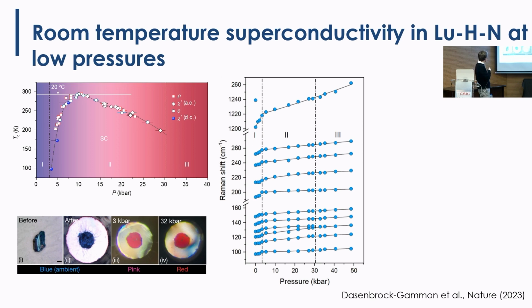They were saying that the sample had a very weird color change. So it was going from blue to red, okay? And then they also measured the Raman, and there were some phonons around 250 centimeters minus 1, some others below, and some very high energy phonons around 1,200, things like that. So this was the evidence they had, okay?